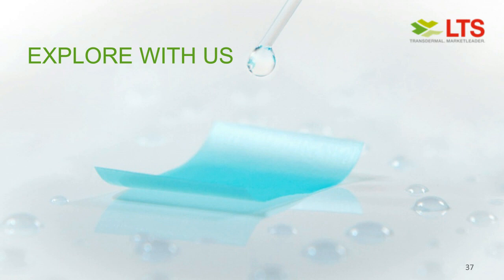So, no, in general, no, because in these zone 4 conditions, these products are tightly sealed in the pouches, so the moisture impact would be really limited due to the primary packaging. The temperature really depends on the API stability, but since it's still a solid dosage form, very often stability is pretty similar to those tablets. So there's definitely no general limitation to go into that, especially with the foam OTFs which I have presented to you. Different humidity levels, even very dry or very high, would be less of a problem after opening the pouch until the patient takes the medication.